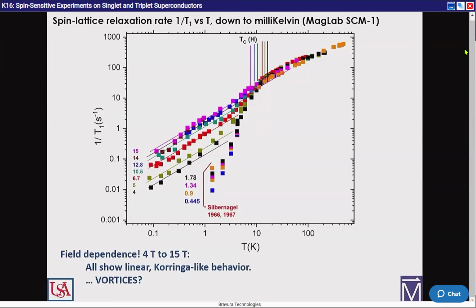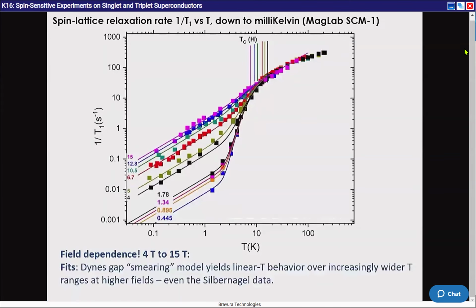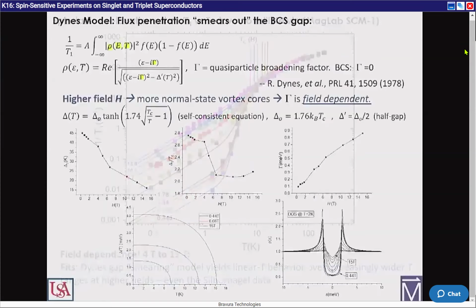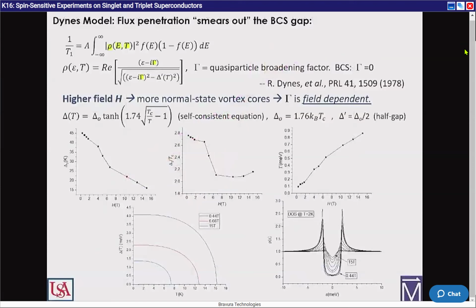So we come up with a model that thinks about that. And when we apply that model, lo and behold, we get a really good fit to our data, including that linear behavior at lowest temperatures. We even fit the Silbernagel data. So, bet you want to know what this model is. It's nothing really new. Dynes, this is something a lot of groups have done.